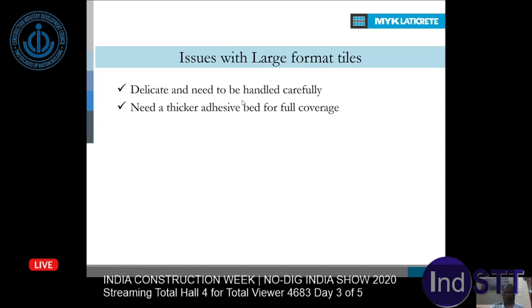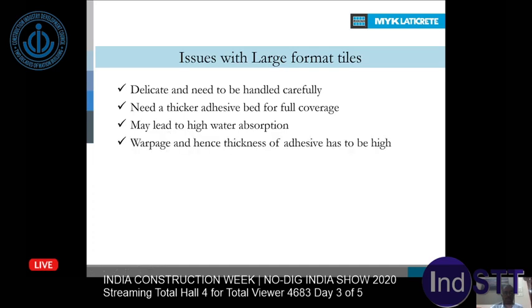Otherwise, you will not get the full coverage. And also, as you go with the thick bed and long workability, it's also going to go with high water absorption, so we have to keep that in mind. The moment you talk about high water absorption, there is a possibility of warpage. To avoid that, make sure that we have a high thickness adhesive that doesn't give away a lot of water. And if you allow thickness and water, then the shrinkage problem is always there.